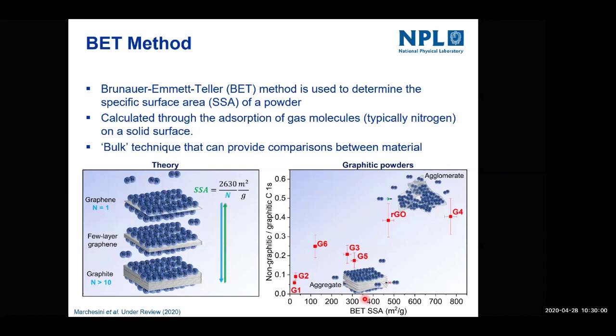Whereas other materials that may be more defective or have more sp3 content can have a much higher SSA value. And this is because of, as we see here, the non-graphitic versus graphitic ratio. Generally, you see this trend of higher surface area with higher amounts of non-graphitic material. So this is, again, a powerful technique to look at, and it's a good way of comparing different materials and even the same material batch to batch. And BET will vary depending on several measurands, but again, it's about taking the SSA, that's the value that you take away from using this technique.